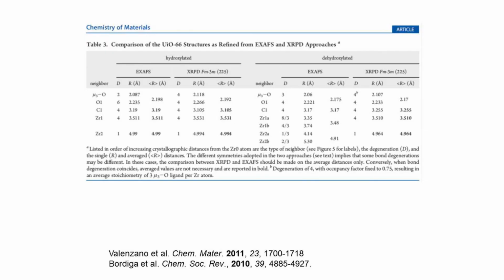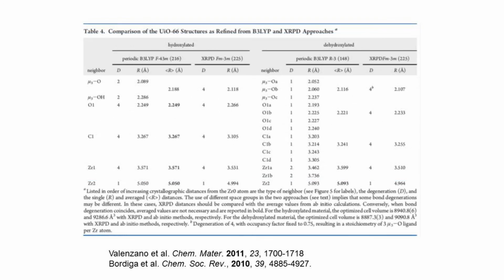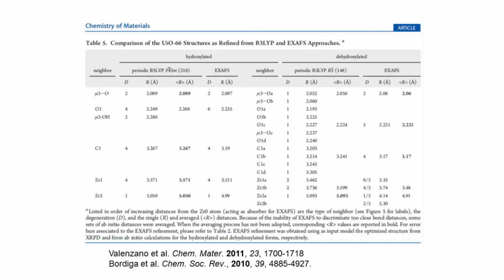Okay, I will not discuss these results because they are very boring, but it is the comparison between EXAFS and powder diffraction, between powder diffraction and ab initio calculation, and between ab initio calculation and EXAFS, in order to check that the two experimental techniques and the theoretical ground agree with each other. And it is very important because EXAFS and diffraction see two different things.